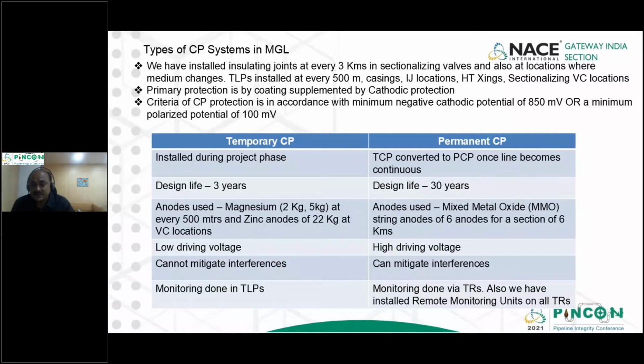For anodes, we use 2 kg, 5 kg magnesium anodes every 500 meters, and zinc anodes of 22 kg at the wall chamber locations. Every sectionalizing wall will have TCP of zinc anodes of 22 kg. For the PCP, we have MMO, mixed metal oxide anodes, 6 anodes for a section of 6 kilometers. The PCP advantage is that it can mitigate interference to a large extent.